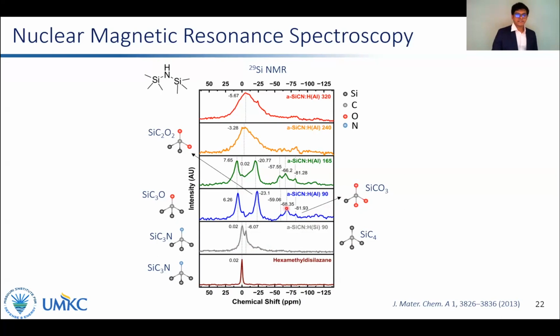The samples collected from the aluminum foil were significantly contaminated with oxygen, as noticed from peak resonance assignments made from the chemical literature. Interestingly, the silicon resonances broadened for samples fabricated at higher temperatures, which indicates the onset of a high degree of cross-linking at about 240 degrees Celsius.